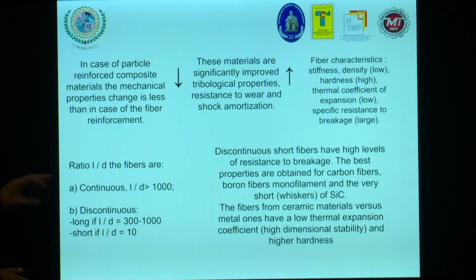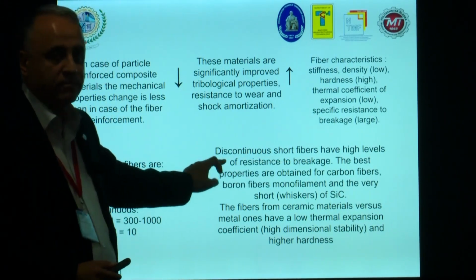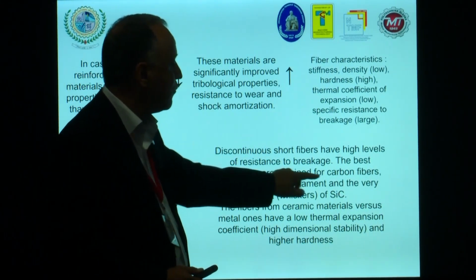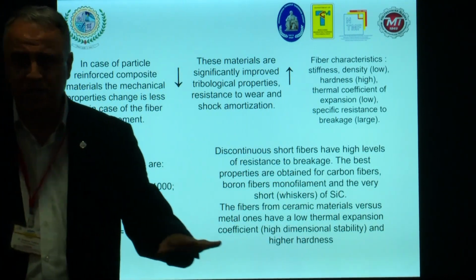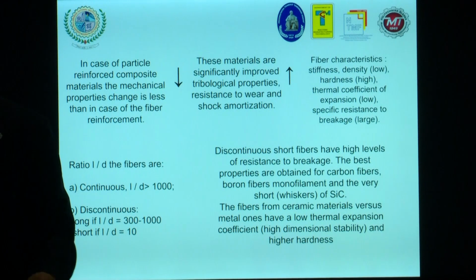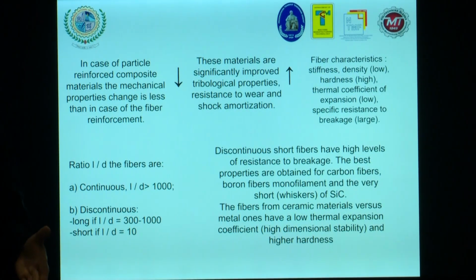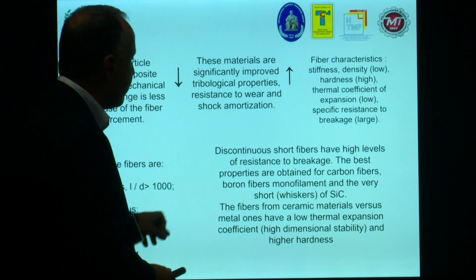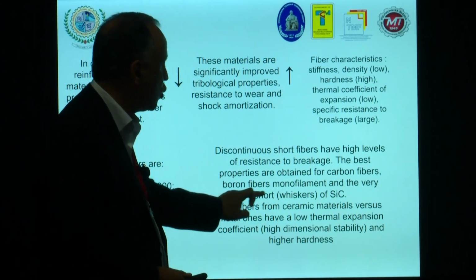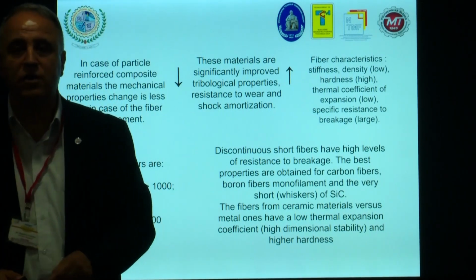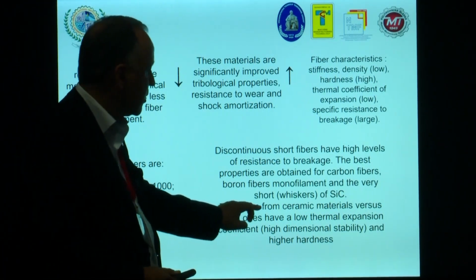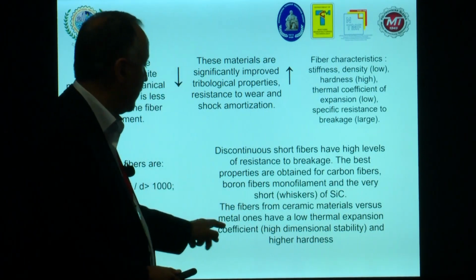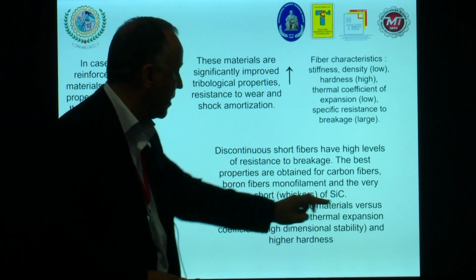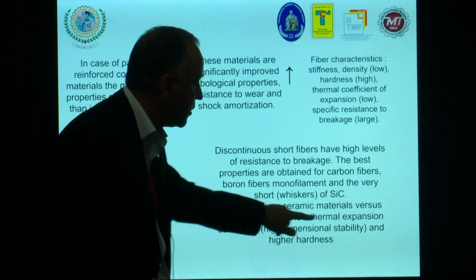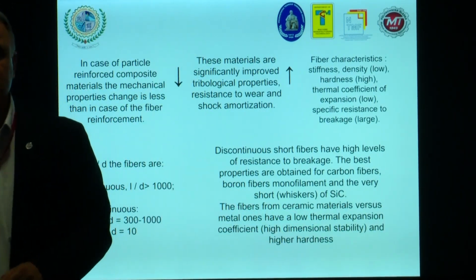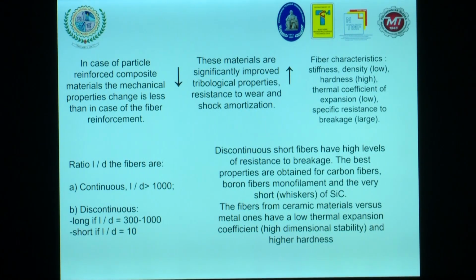Discontinuous short fibers have high levels of resistance to breakage. The best properties are obtained for carbon fibers; many times during the lectures this week we talked about carbon fibers. Boron fibers, monofilament, and the very short whiskers of silicon carbide. Fibers from ceramic material versus metal have a low thermal expansion coefficient, I mean high dimensional stability and higher hardness. But of course, because we are talking about ceramic.